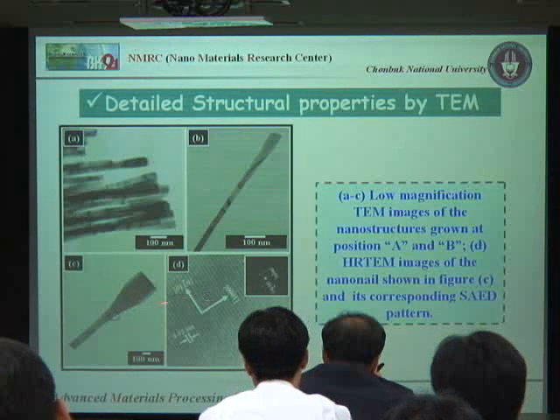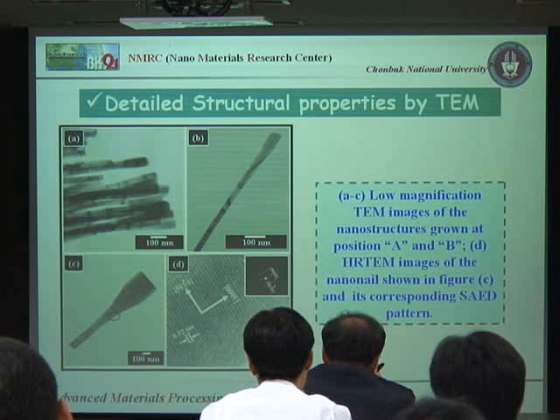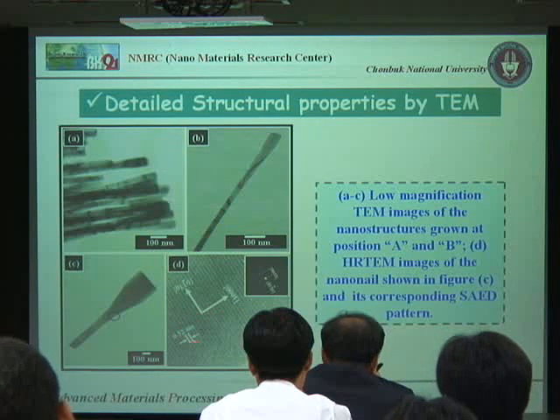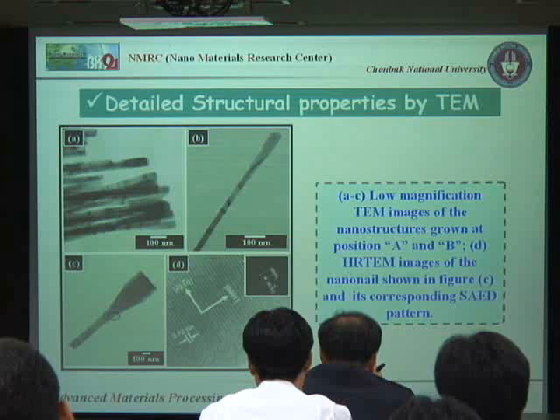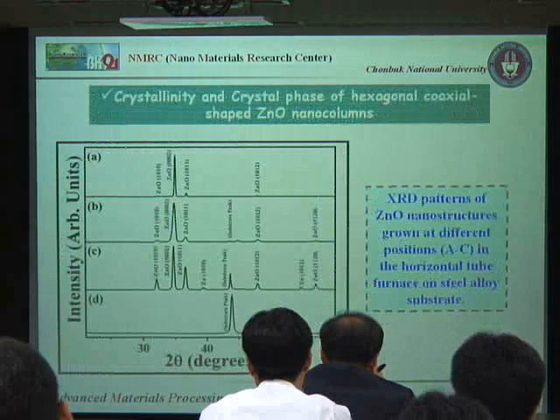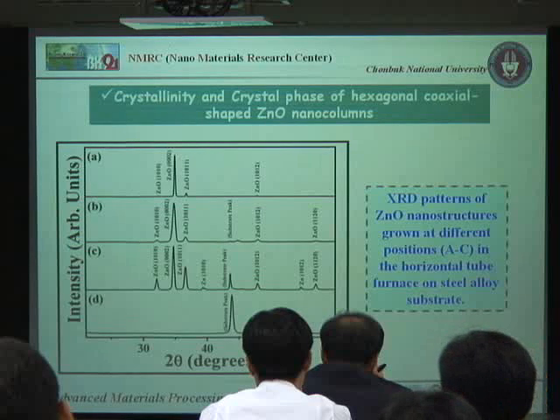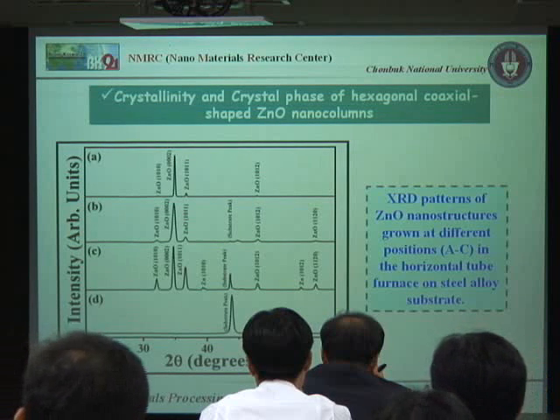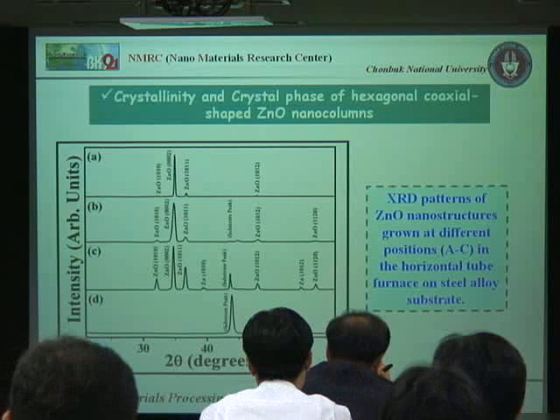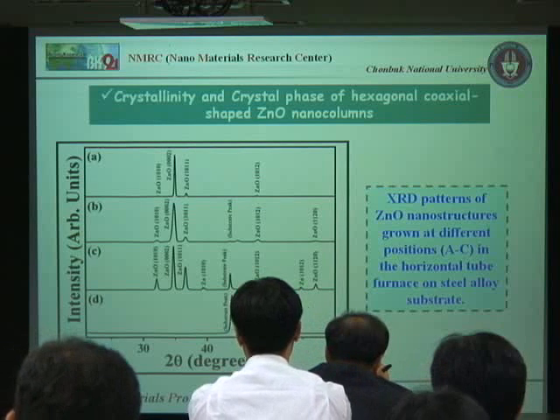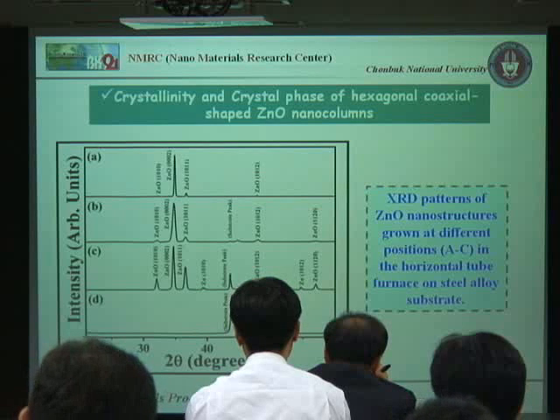B. We got that these nanonails have grown along the 0001 direction, and it has a perfectly hexagonal face. Because the lattice distance between the two fringes is about 0.52 nanometer, which is equal to the lattice constant of zinc oxide. So we can predict that our grown nanostructures are purely hexagonal with vertices. The crystallinity and crystal sizes of our grown nanostructures were observed by XRD pattern, and we got that all the nanostructures are grown along the C-axis direction.